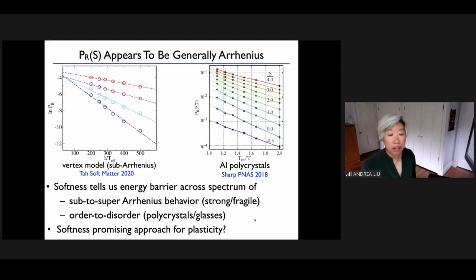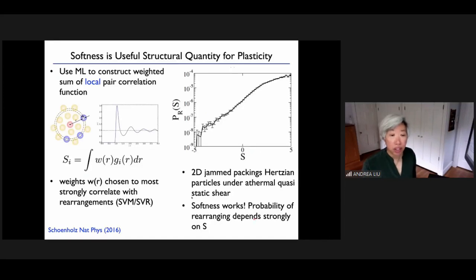Okay, so the question is, can we use a similar quantity to look at plasticity at zero temperature? So we did the same thing. We construct a pair correlation function. For the weights, I should have said how we trained the system: by showing it particles that are rearranging and particles that have not rearranged for a long time, or in this case, a very long strain.